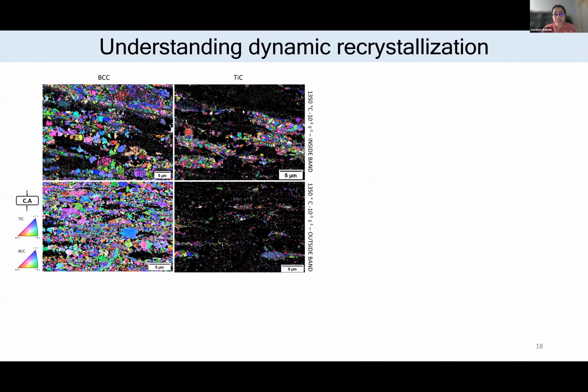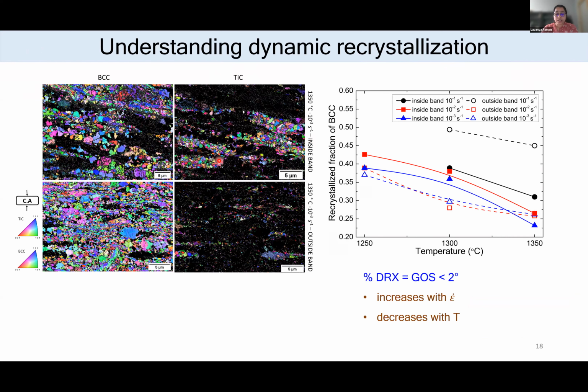Now to understand this dynamic recrystallization or the softening mechanism, we did EBSD analysis. We have tried to index the BCC and titanium carbide phase. Using the grain orientation spread, we can calculate the recrystallized fraction. As we can see, the recrystallized fraction of the BCC phase increases with increasing strain rate and decreases with the temperature. From this EBSD pattern, it is clear that at the interface of BCC and titanium carbide, we have very fine recrystallized grains.